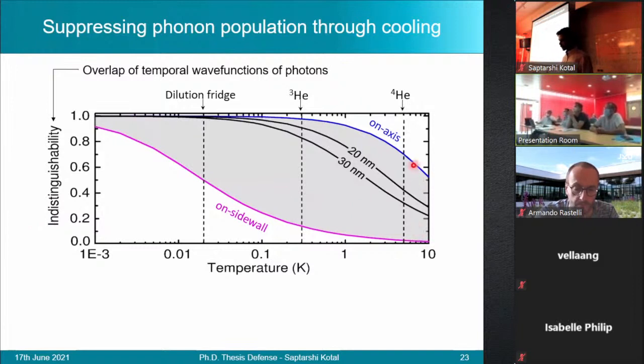So here we notice that when the quantum dot is on the very axis of a nanowire, which is the best position that it can be, in the best case scenario, we obtain only about 70% indistinguishability. And even if the quantum dot is shifted by about 20 nanometers from the axis, we obtain an indistinguishability as low as 40%. And for a quantum dot positioned close to the sidewall of the nanowire, it is practically impossible for us to produce indistinguishable photons.